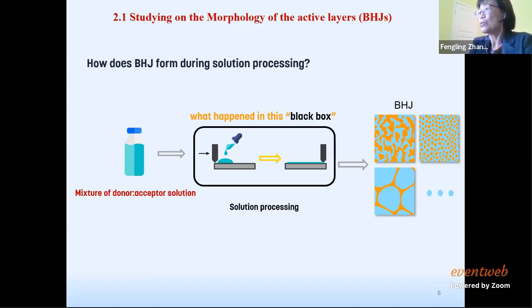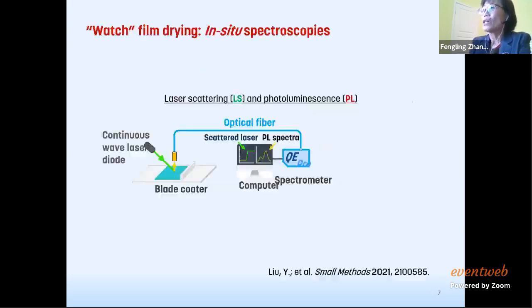Therefore, we are interested to know what kind of parameters control the drying process, in order to further improve the device performance. So we want to watch the film drying. Then we need some tools to do that. We have a homemade in situ spectroscopy setup, as shown here. With this equipment, we can collect the photoluminescence signal from the active layer, and also the signal from light scattering.